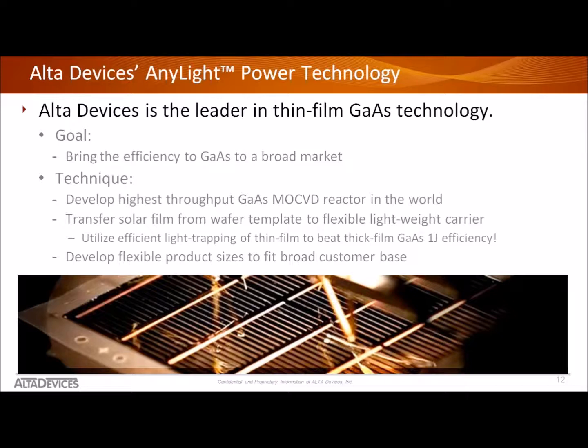The wafer gives us really clean, high efficiency material, but the thin flexible carrier that we put it on allows us to be lightweight and go on flexible products. There's an additional advantage of this, that by making our gallium arsenide film layer thinner, we actually get a performance advantage over the traditional gallium arsenide. So there's light trapping that occurs when you have a very thin absorber film. Somewhat counterintuitive, but it gives us the world record efficiency of 28.8%.